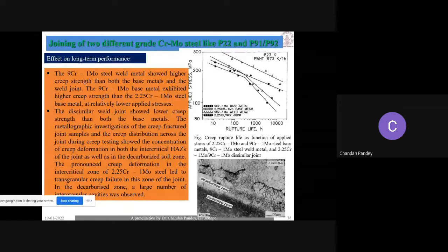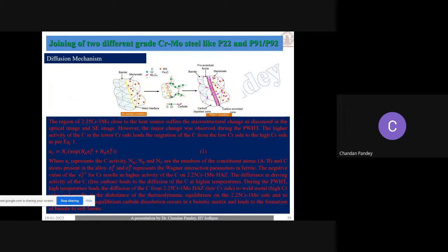we get the failure from the weak region of your heat affected zone. I discussed three different regions: coarse grain, fine grain, and intercritical. So due to the heterogeneity in the mechanical property along the weldment, we get the failure from the region of your intercritical heat affected zone. Suppose this one is your weld joint, and this one is the region of your heat affected zone. Here, this is the CGHZ, this is the ICHZ. Here you will get the ICHZ.